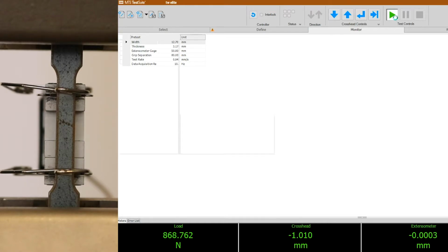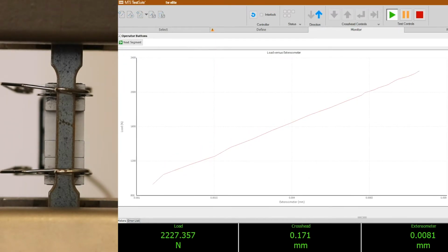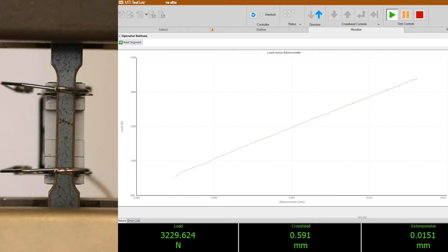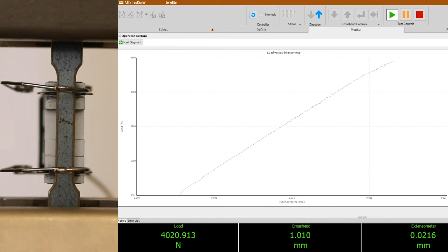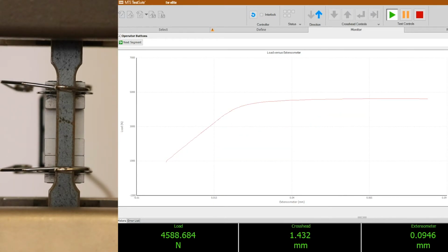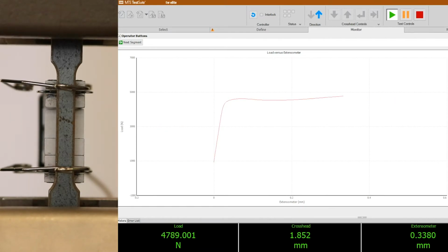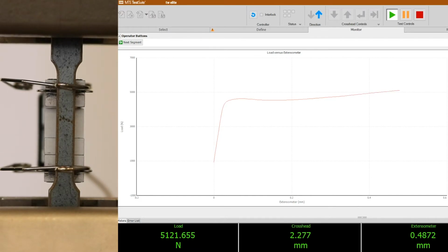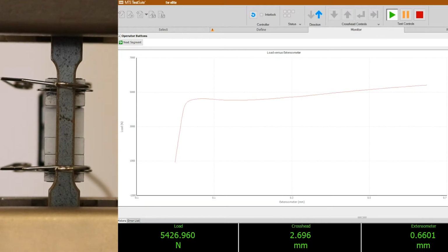So here we go. Okay, so our test is now running and we're in the linear portion of the curve, so you can see a nice linear line between force and extension there. And now the curve is flattening out, so the sample is yielded, and now the curve is completely horizontal, which means the sample is elongating continuously with no additional applied force. And now we're in the strain hardening region of the curve, where load is increasing again with applied extension.